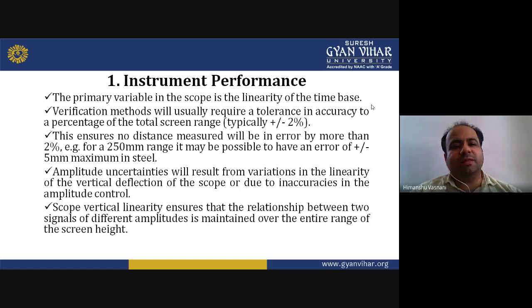Verification methods will usually require a tolerance in accuracy, as a percentage of the total screen width, that is a result of plus or minus 2%. Only this tolerance is allowed. This ensures no distance measured will be in error by more than 2%. For example, for a 250 mm range, it may be possible to have an error of plus or minus 5 mm maximum in steel. So only 2% of error is allowed.